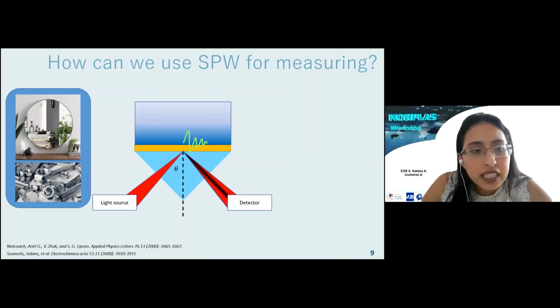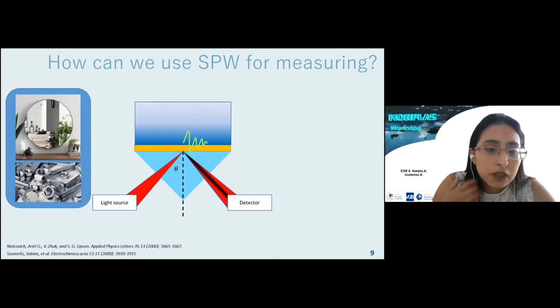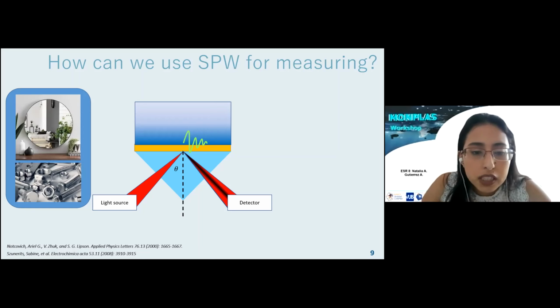But if you think in our daily lives, we don't see this because, for example, in mirrors or also in metallic surfaces, we see a shiny surface instead of a black one. So what's going on? What happens is that we require special configurations to be able to generate these effects, such as this one that we are observing here, which is the prism configuration. And also we require that the wave vector of the light is equal to the wave vector of the surface plasmon wave. So even if we have a broad light source like this, we will observe that there is only one small gap that is going to be transmitting its energy to the surface plasmon wave.